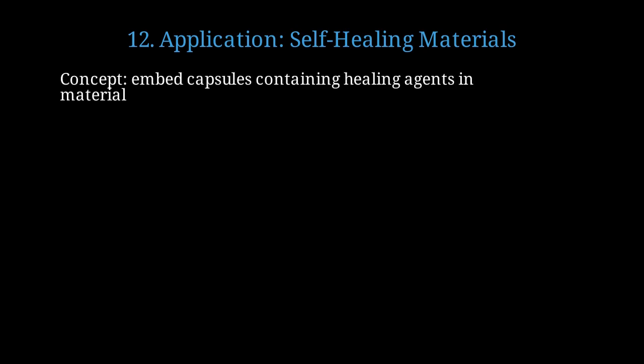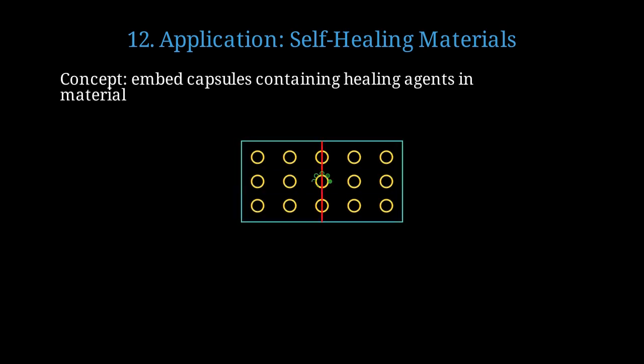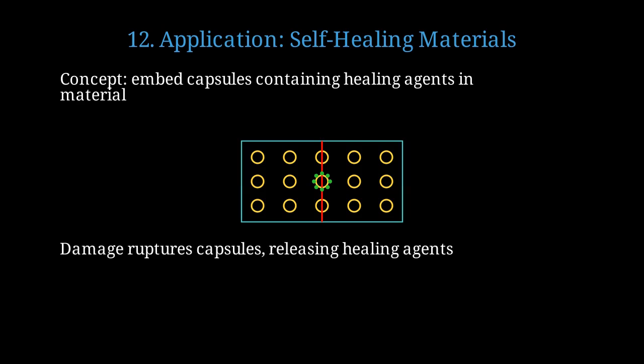Self-healing materials use microcapsules filled with repair agents that activate upon damage. Capsules containing liquid monomers or adhesives are embedded throughout the material matrix. When a crack propagates through the material, it ruptures capsules, releasing healing agent that flows into the crack. The mechanical stress from crack propagation ruptures nearby capsules automatically. The released monomer contacts a catalyst in the matrix and polymerizes, sealing the crack.